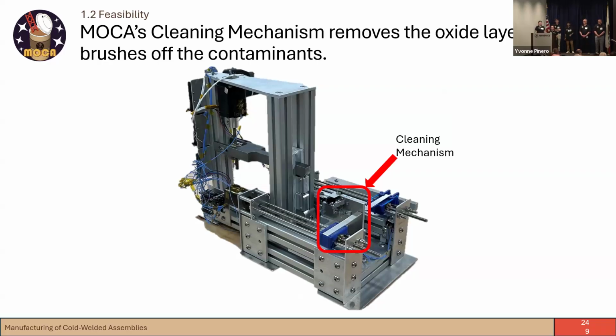As for why it's important to remove the oxide layer, when you remove the oxide layer in the cleaning mechanism, it allows the two metal members to create a stronger and cleaner weld. And since it's in vacuum, the oxide layer will not grow back, which allows the mechanism to take advantage of the exposed metal members and begin to create that weld.